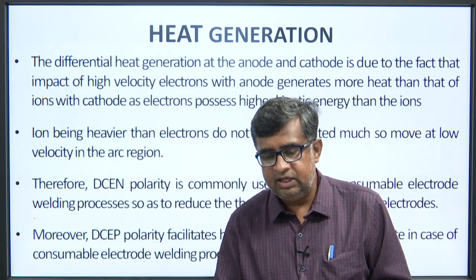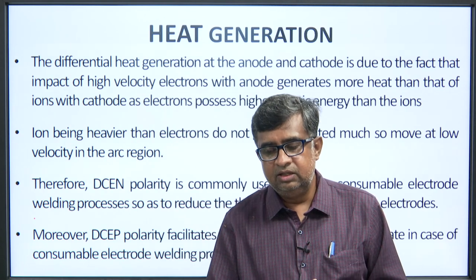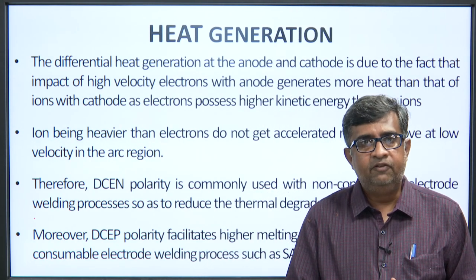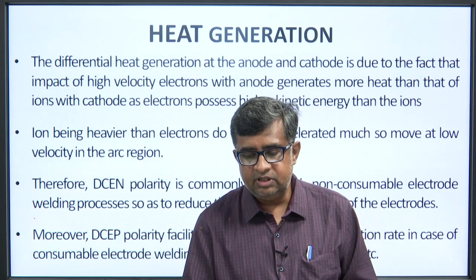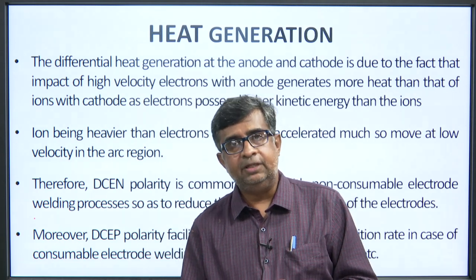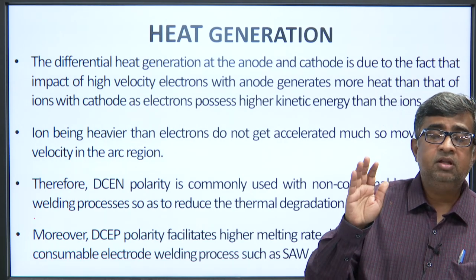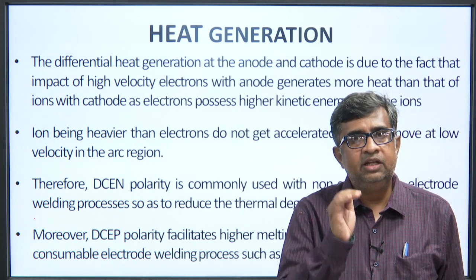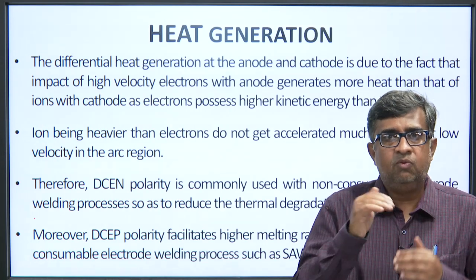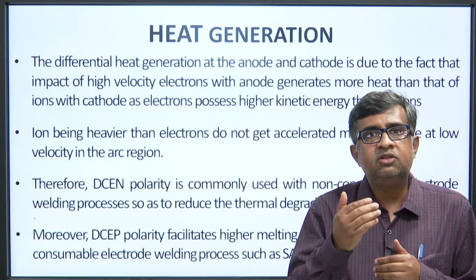DCEN polarity is commonly used with non-consumable electrode welding processes to reduce the thermal degradation of electrodes. Moreover, DCEP polarity facilitates a higher melting rate and deposition rate in the case of consumable electrode welding processes such as SAW and MIG. Remember, both have advantages and disadvantages.